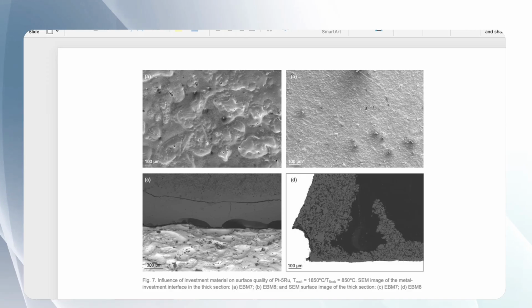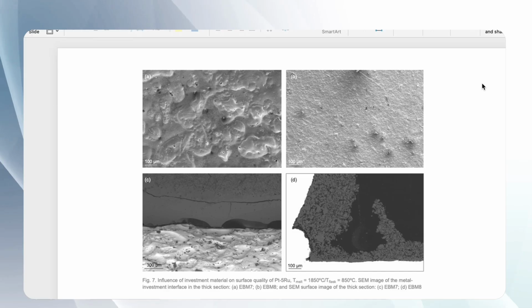Yeah, this diagram shows the surface of the cast part and the reaction with the investment material. Here we see that the surface of cast parts made from platinum ruthenium can sometimes be quite rough, because if there is an overheating of the investment, we get an investment breakdown, and this gives a poor surface quality. So these are extreme examples, but it shows us that casting with platinum ruthenium requires greater care and very good investment materials. We found that there is a big difference in the investment materials, in how strong this reaction with the alloy will be.